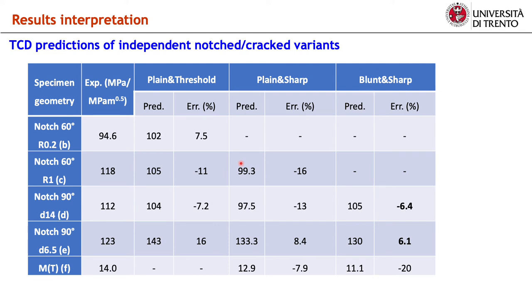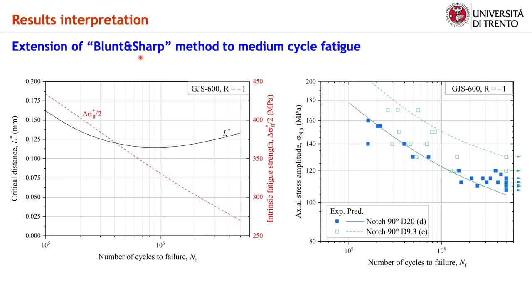This table shows the fatigue strength of independent notch variants and permits to assess the suitability of these three critical distance approaches to predict the notch fatigue resistance of DCI. A systematic comparison is possible only for variants D and E used in either of these approaches. Interestingly, the blunt and sharp approach is the only one able to keep the absolute relative error well below 10%. Conversely, the plain and threshold and the plain and sharp predictions are affected by larger errors, since these latter two approaches are influenced by fatigue damage mechanisms occurring in plain and empty specimens that are scarcely representative of those taking place in notched coupons. The blunt and sharp approach was then successfully extended to the medium cycle fatigue regime, with predictions in satisfactory agreement with the experimental data.